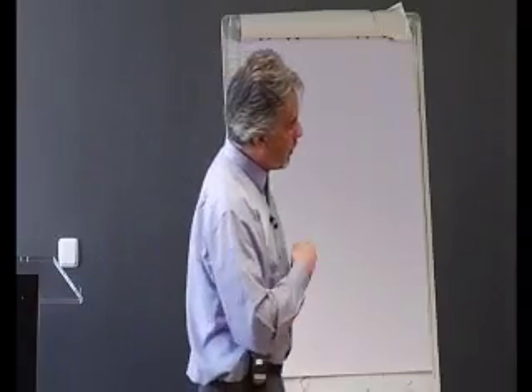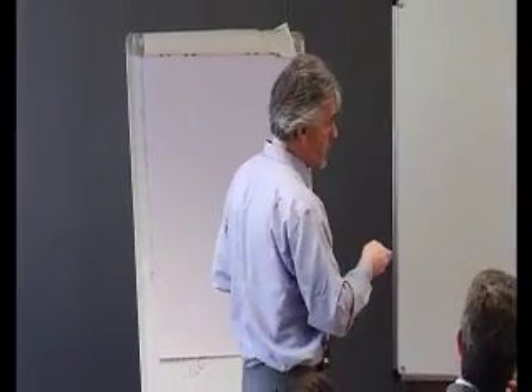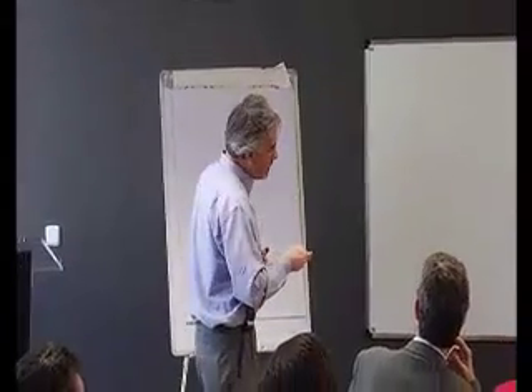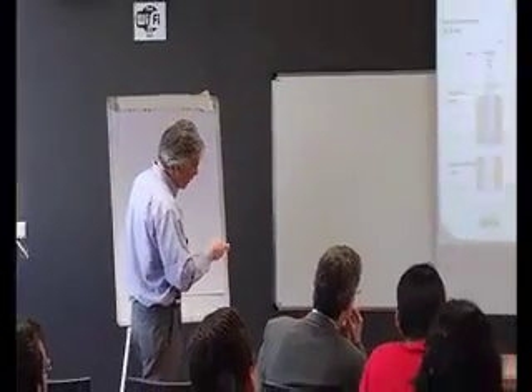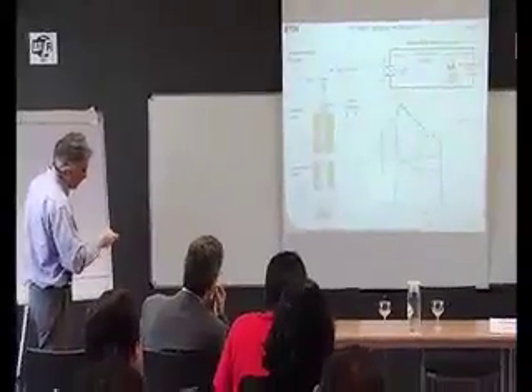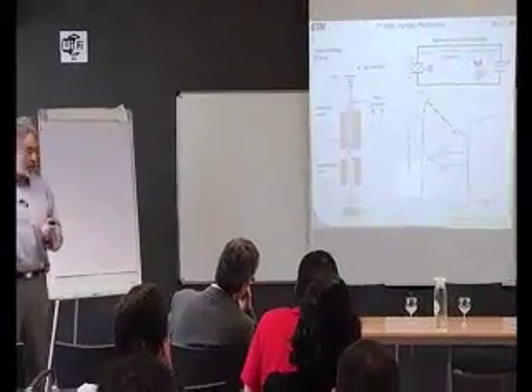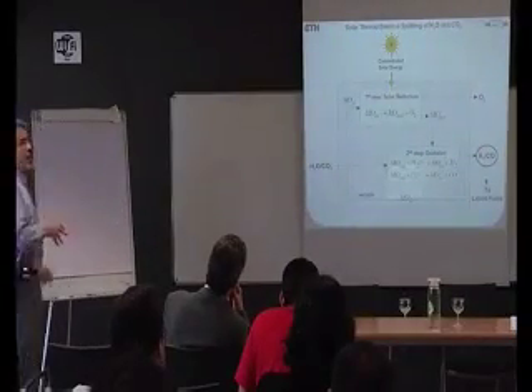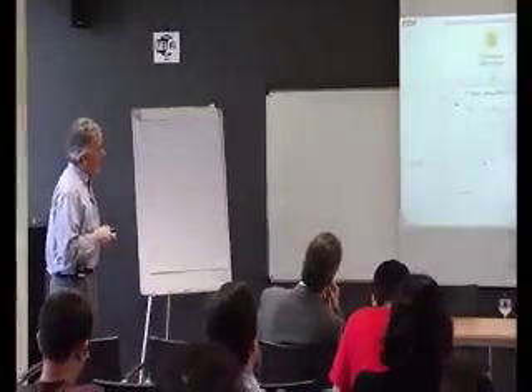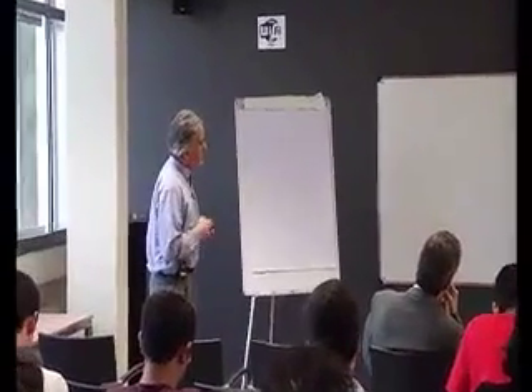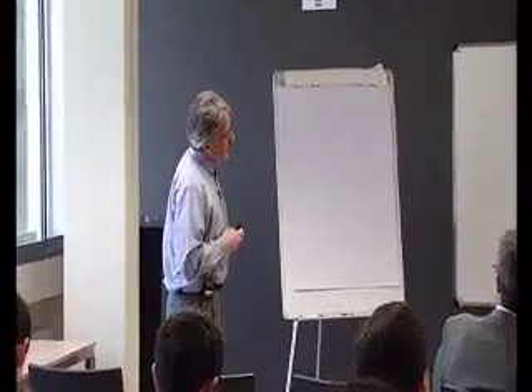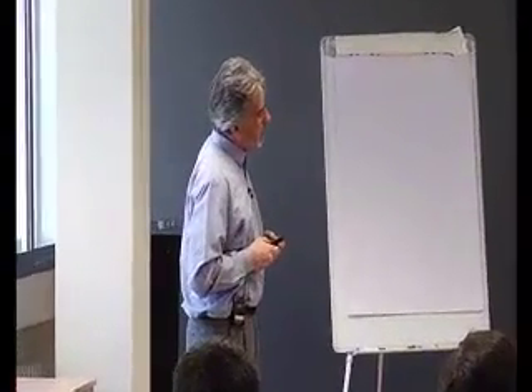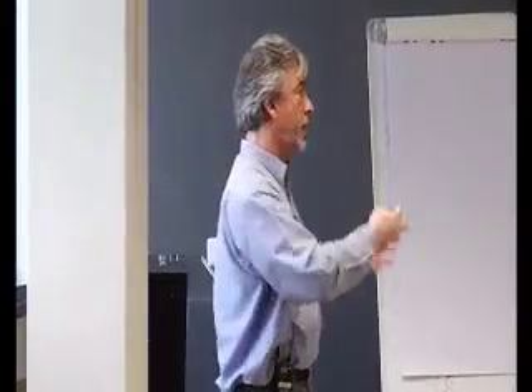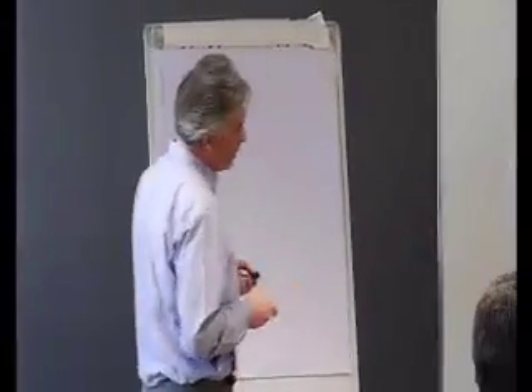This is an example of a run in which we are feeding CO2 instead of water. So we are splitting CO2. Here you see the CO2 reacting, the CO forming, and this is the zinc evaporation rate. Let me come back to the schematic of the redox cycle. And I would like to review very briefly the work that is being done in other labs with respect to this thermochemical cycle.